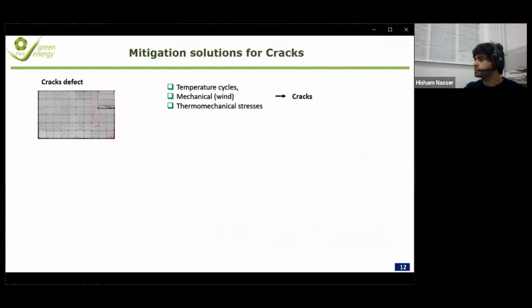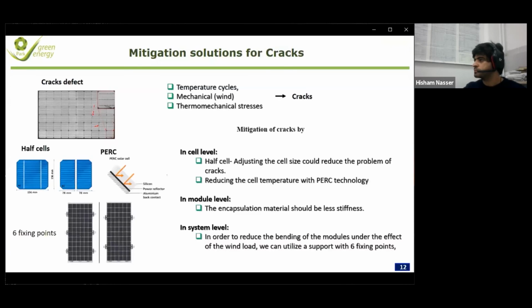During the operation of PV modules, temperature cycles, mechanical stress, and thermomechanical stress are the main causes behind cracks and microcracks in PV modules. As solutions, we proposed some solutions at the cell level, at the module level, and at the system level. At the cell level, we propose to use half cells against full cells in order to reduce the problem of cracks. In parallel, we can reduce the cell temperature by using the PERC technology and also improve the efficiency of the PV module.